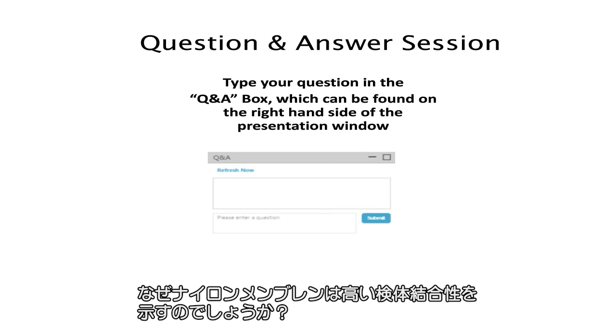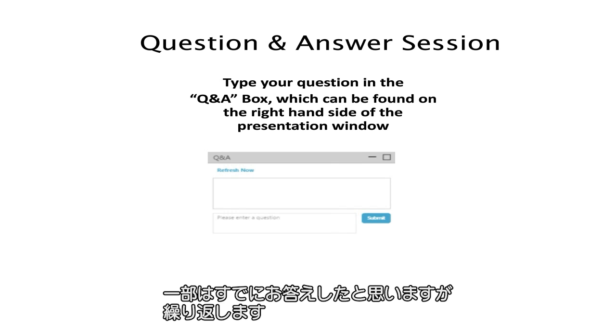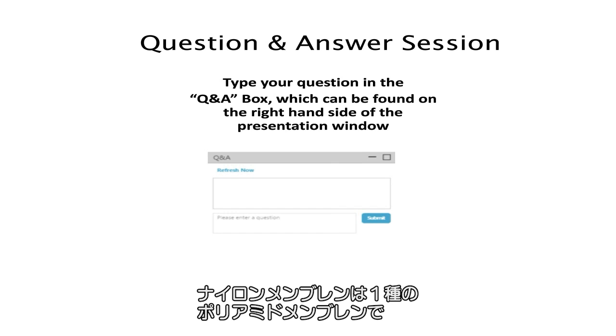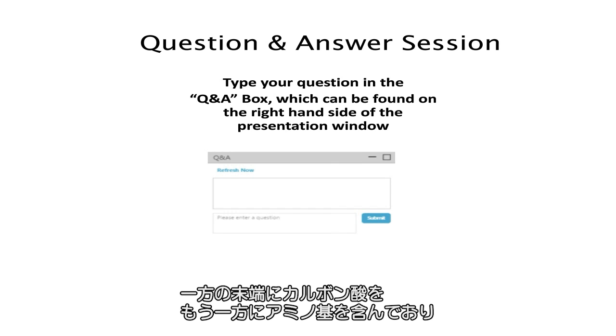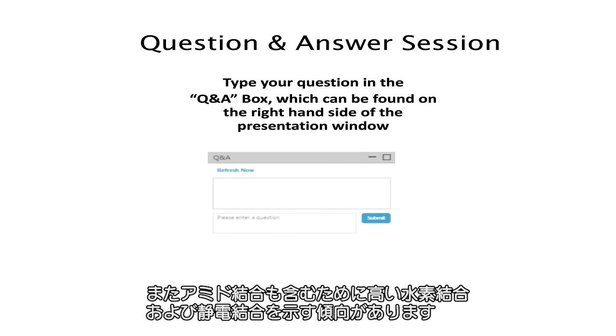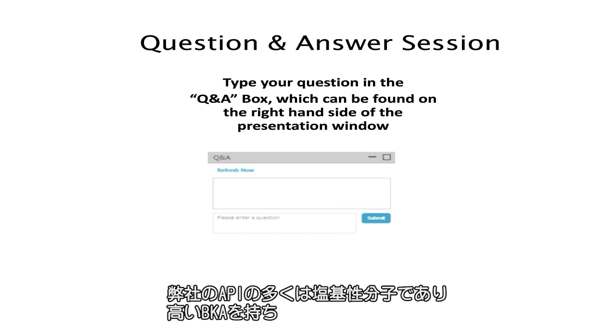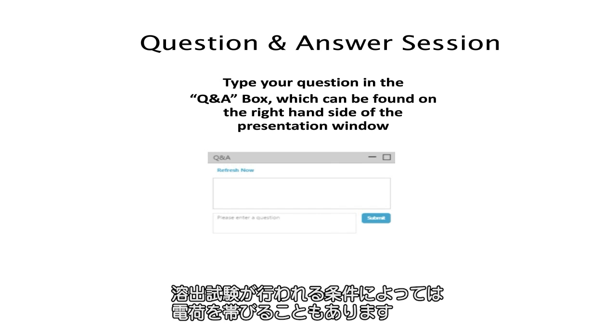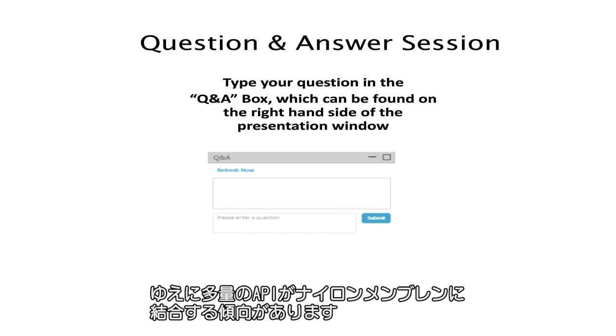Thank you again. And why does nylon membrane show higher analyte binding? I think part of this question was already answered in an earlier segment, but just to repeat, nylon membrane is a polyamide membrane containing a carboxylic acid on one end and an amino group on the other end, as well as containing amide bonds, which tend to show higher levels of hydrogen bonding and electrostatic bonding. Many of our APIs are basic molecules, meaning they have higher pKa's, and they can also be charged depending on the conditions under which the dissolution test is carried out, and hence your APIs can tend to show a higher amount of binding to nylon membrane.